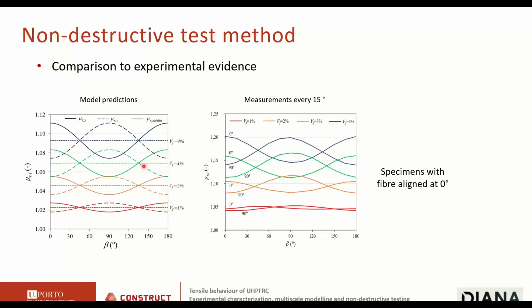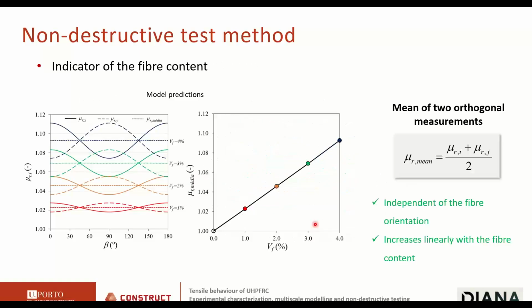The green curves correspond to a specimen with less fiber content. This is what we get from the measurement. It's not far away from what we predict with that complicated equation, so we see the same trends. Also very important, the theoretical model predicts that if we average two orthogonal measurements of the relative magnetic permeability, a measurement at 0 degrees and a measurement at 90 degrees, you get these lines that are nearly horizontal.